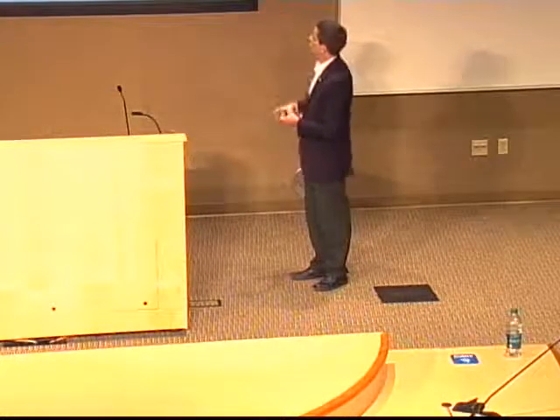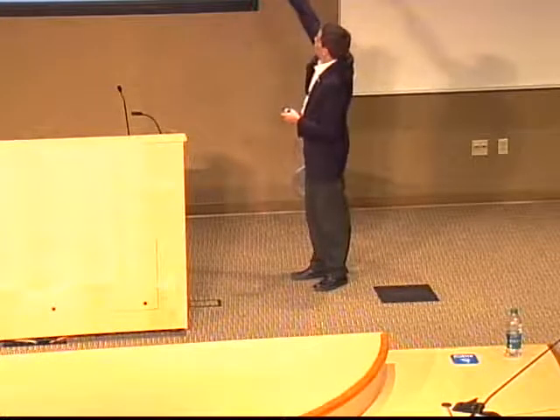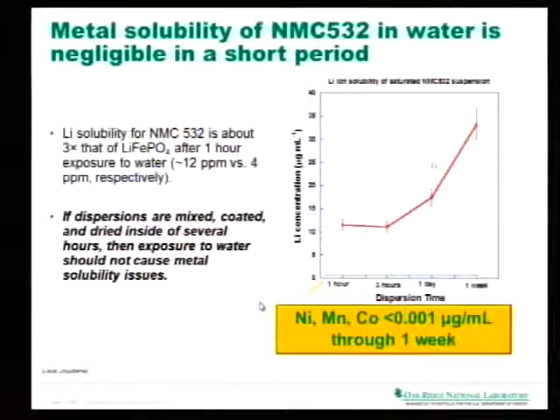This is some lithium concentration over a full week here. You get up to about 35 microgram per milliliter. That is acceptable for the lithium. You look for the nickel, manganese, and cobalt. It's not detectable. It's below our detection limit. So we're all set. Everything is good on there.